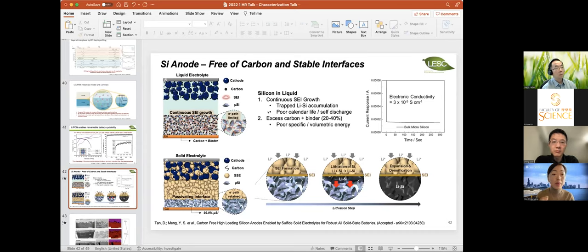Remember in the first cycle, the system is under very high pressure. We reported in the paper about 30 to 50 megapascal. So the lithium comes in and the silicon will become a mixed conductor. So it's really important that at the beginning, the conductivity of your silicon has to be in this range. It cannot be too low, because some of those nano silicons have extremely low electronic conductivity, and people might find difficulty in putting the first few lithium in. So the initiation of the lithium silicon is very important.